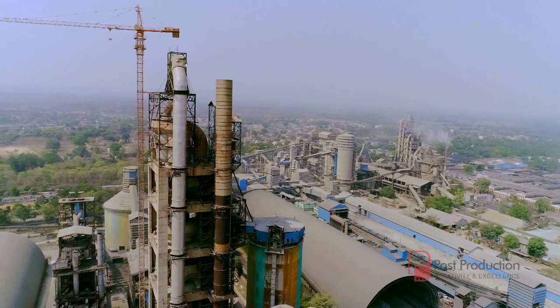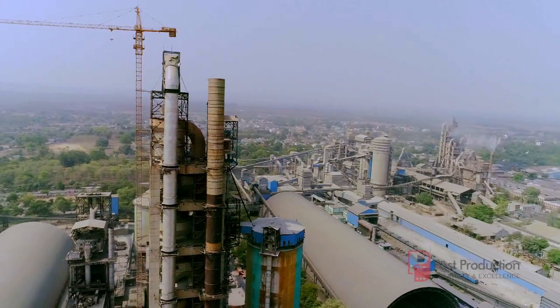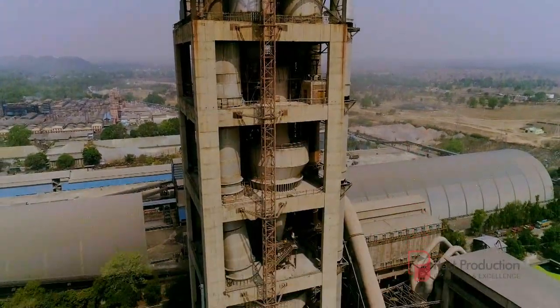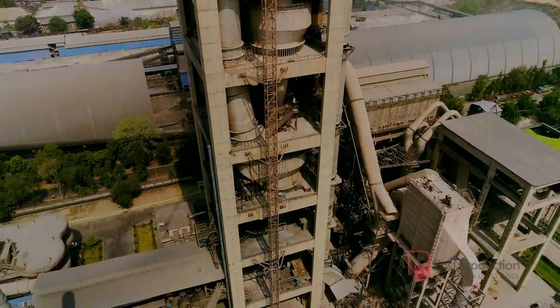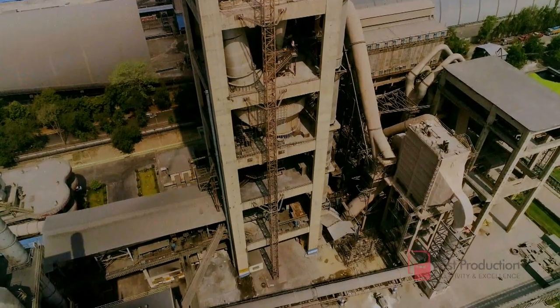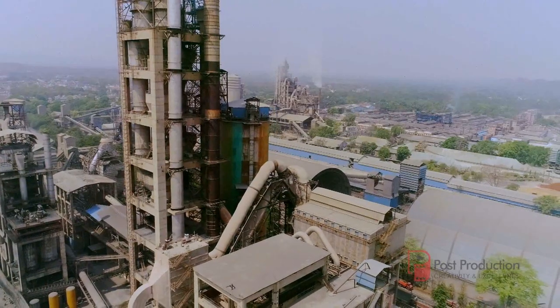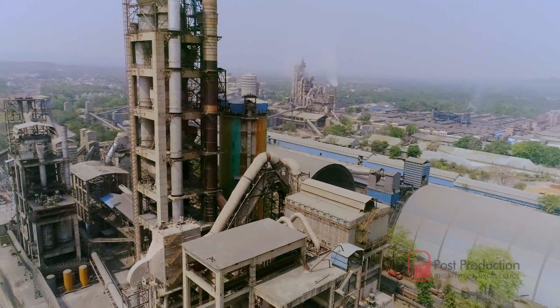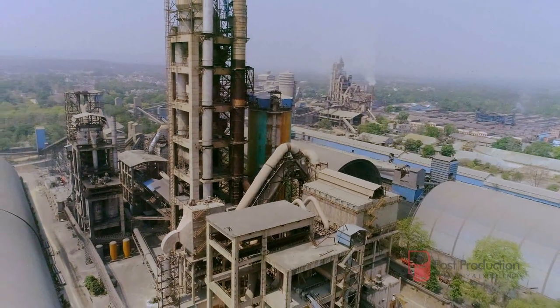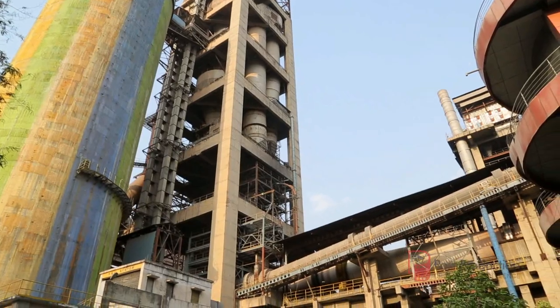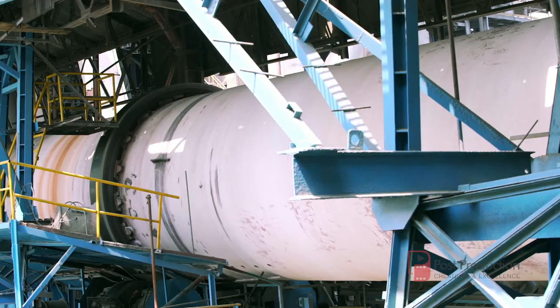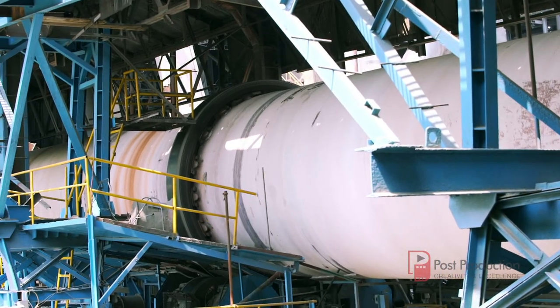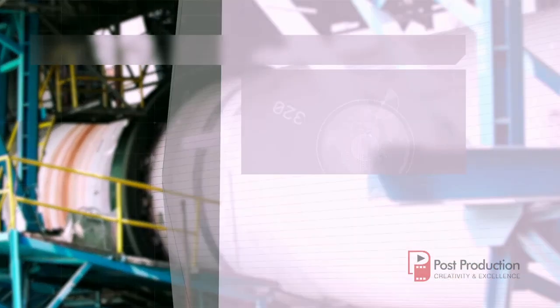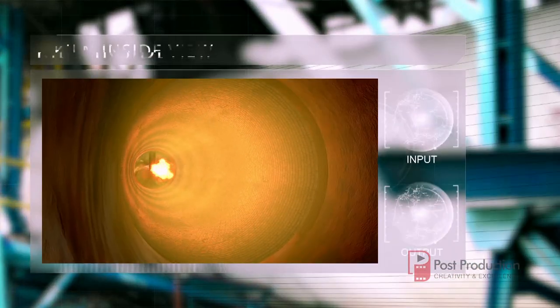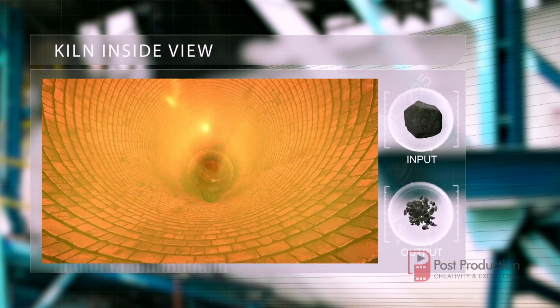From here, the limestone powder is passed through the 7-stage preheater tower where it is heated to temperatures of around 800 to 900 degrees centigrade. Nearly 90% calcination, that is, removal of carbon dioxide or CO2 from calcium carbonate or CaCO3, takes place before entering the kiln.